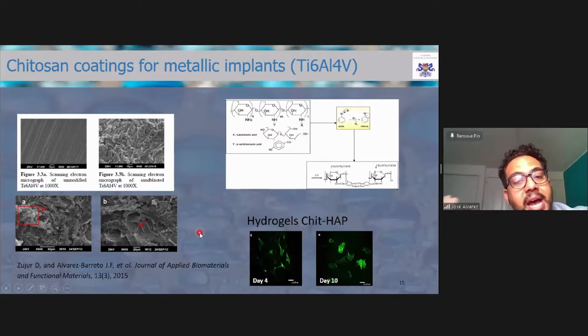Now, using the same idea, we also created hydrogels with hydroxyapatite. Hydroxyapatite is an analog of the mineral component of bone. And we also cultured mesenchymal stem cells on them, and we followed their differentiation. The idea here was to create some kind of bone filling for maxillofacial applications, so that we could have something injectable, for example, for a jaw defect or something like that.